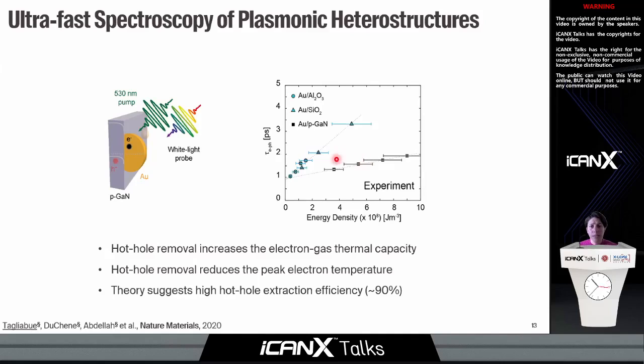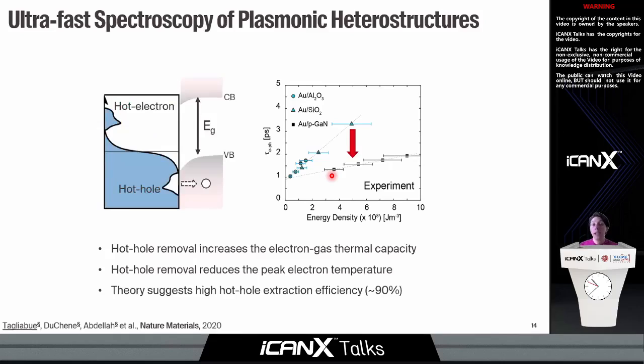So we performed this experiment in two different cases. We had our gold p-type gallium nitride system where we know we are extracting holes, and then we have gold nanoparticles on an insulating substrate where we are not removing any holes. And what we observed is that the slope of the increase of the electron-phonon coupling time with the energy density that is absorbed in the metal is very different. And it's much lower for the gold p-type gallium nitride. This is very important information because it's telling us that the electron gas thermalizes to lower temperatures in the p-type gallium nitride system than in the insulating one.